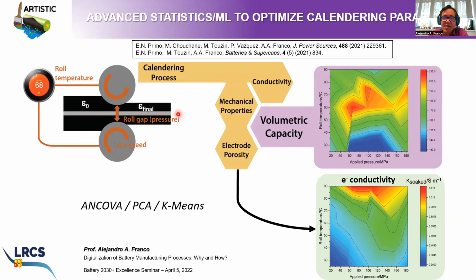And you can investigate how these parameters, together with the roll gap, which is related to the pressure that you apply in the electrode upon calendering, will impact, for example, the volumetric capacity of your electrode or electronic conductivity. And once again, you can build these very nice maps, right? They are actually 3-dimensional or 4-dimensional, but here I'm just showing 2 dimensions. I'm showing the roll temperature and the applied pressure. So it's a heat map.